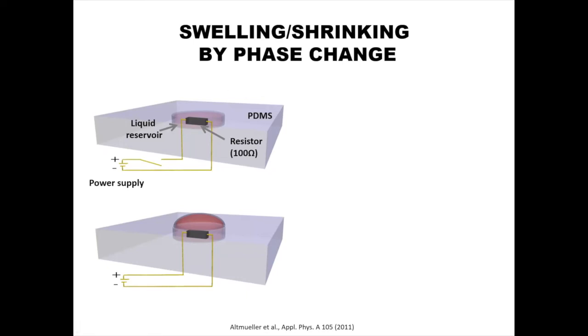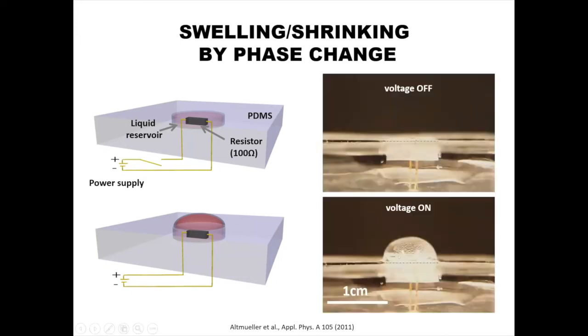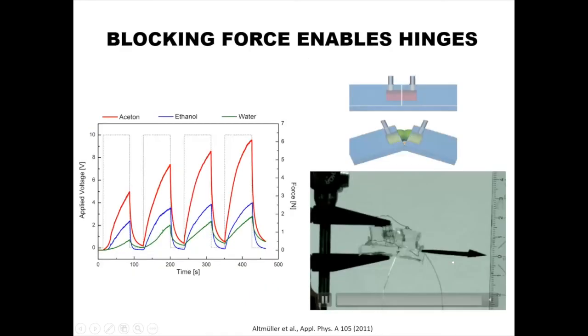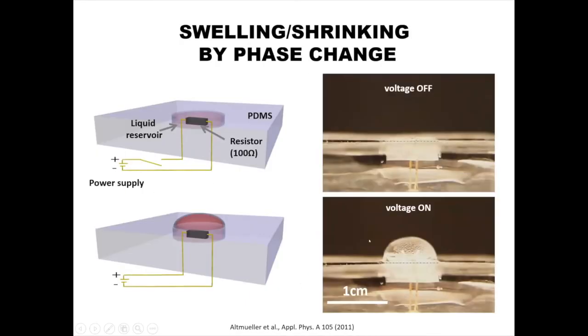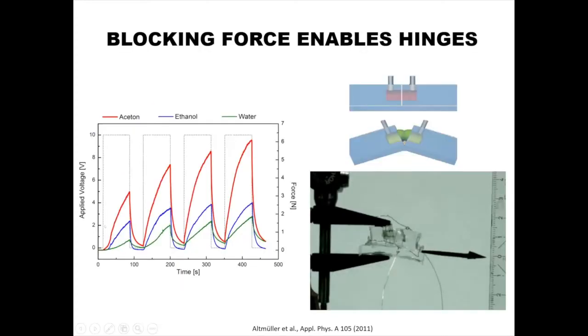And what happens if you heat it up, it's like what you do in a pressure cooker. You see that this membrane expands, and you have a volume expansion. Since the liquid evaporates and the gas expands, you have a volume expansion of about 120%. And we were using this to create a little actuator. What you can see here is these bubbles pushing against each other, and we're making this little hinge where we can really have a nice bending motion.